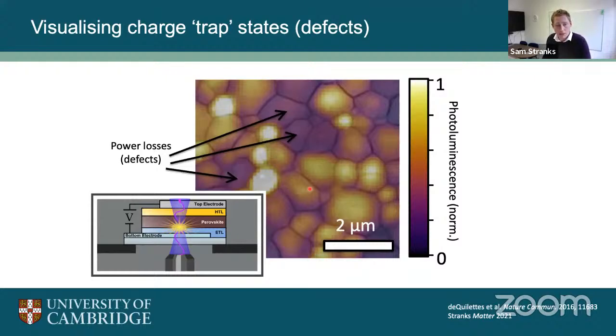And that gives us important information, because where we don't have much light coming back out, in these dark regions, sorry, my mouse is a bit slow. You can see where the arrows are pointing, in these darker regions, this is where we have lots of power losses, because we have carrier traps. So these energized electrons fall into traps, and then they lose their energy to heat. And so they wouldn't contribute to the solar cell's power. Whereas there are other regions that are really bright and luminescent, and that's good. That means we have very few defects in those regions. So this tells us that we need to design the devices or the materials so we have a uniform and bright image, ideally. And so this is a good technique to assess how good these devices are.